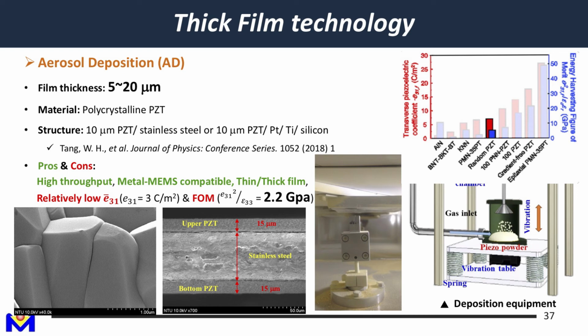Here we put the piezoelectric powder, PZT powder, into this bottle, and it's suspended and with a high pressure gas blown to bring the powder into this vacuum chamber. Because of the pressure difference, the particles will be accelerated, and when jetting out from the nozzle, it will hit the substrate here, upside down, with very high speeds. With this kind of deposition method, because of hitting the substrate at high speeds, it can deposit a very compact film, and the impact also causes some local heat, so it also helps with the sintering or crystallization. Of course, after this process, you still need to do annealing or heat treatment to get a perovskite crystal state, and then you also need to do the poling process.